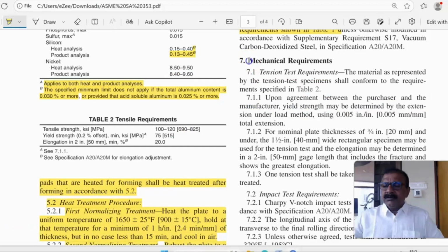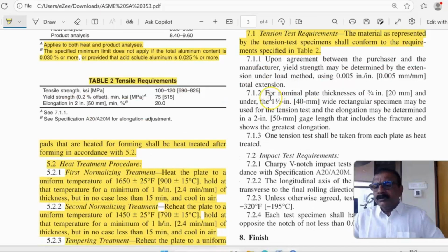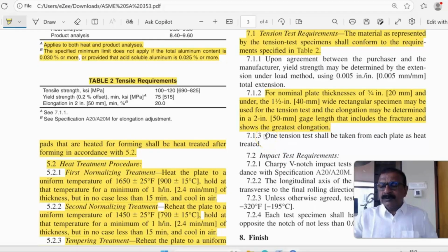Then mechanical requirements. First we'll see the tension test requirement in table 2. This is our table 2, tensile requirements. Tensile strength is very high, you can see 690 to 825 MPa. Yield is 515 MPa, and elongation 20% in 2 inch. Here there is one more requirement for tensile specimen. For nominal plate thickness 20 mm and below, a 40 mm wide rectangular specimen may be used for the tension test, and the elongation may be determined in 2 inch gauge length that includes the fracture and shows the greatest elongation. Here frequency of testing is also given. One tension test shall be taken from each plate as heat treated.